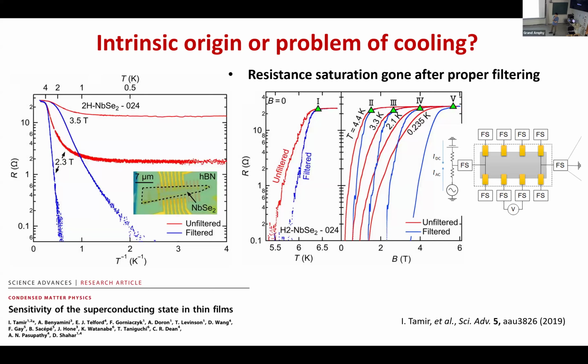Yes. So when I first saw this paper, I thought, okay, everything is over, right? Because this paper just showed that for niobium diselenide, the same sample, when you filter it or not, either you see it or you don't see it. So you have the saturated resistance if you don't have good filtering, and if you improve the filtering, then you can kill this effect. So this looks like the so-called anomalous metal.